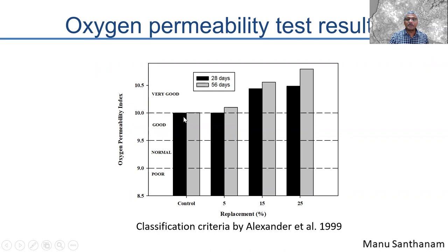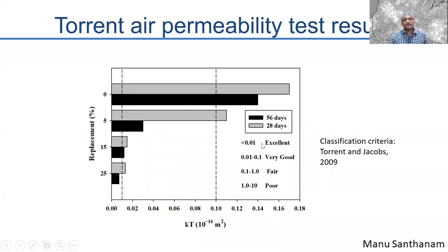You can see that compared to control, all the concretes with bagasse ash give you a much higher OPI value, which means that you have produced a concrete that is of good quality with respect to gas permeability. Another air permeability test, called the Torrent air permeability test, was done for all the blends. And you see here again that the permeability coefficient, which is plotted here, reduces as you increase the level of replacement of cement by bagasse ash.